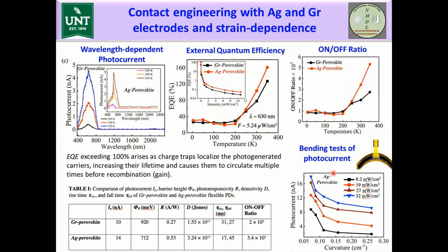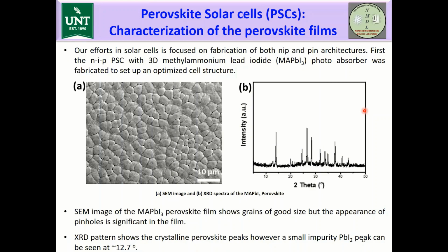Now, since these photodetectors were fabricated on flexible polyimide substrates, we exposed them to bending and checked the photocurrent with different bending curvature and with different fluence of incident light, and that variation can be seen in this figure. So the next part of our work is perovskite solar cells.